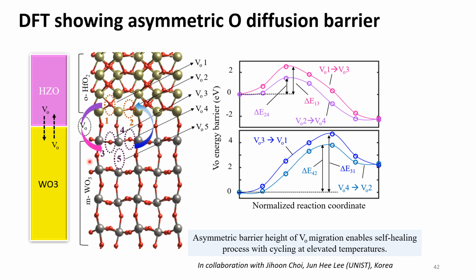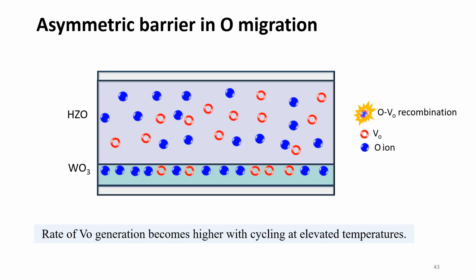So we are clearly seeing an asymmetric behavior in the vacancy migration, or asymmetric barrier for vacancy migration across this HZO tungsten oxide interface. Now, why is this asymmetric barrier so important? Let me try to explain this in terms of oxygen migration. Say we have HZO on top and tungsten oxide at the bottom. As we keep cycling the device, we keep generating more and more oxygen vacancies in the HZO film, and this phenomenon is even worse at higher temperature, for which the device breaks early. So let's see what's the role of tungsten oxide here.